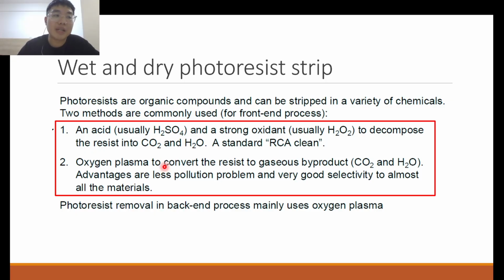This is something similar, just that in this case it is the use of oxygen plasma, because plasma species in a plasma are high in energy, so they have more than enough energy to trigger the oxidation reaction to convert your organic compound, that is your photoresist, into carbon dioxide and water. This step is also sometimes called etching, plasma etching or oxygen etching.